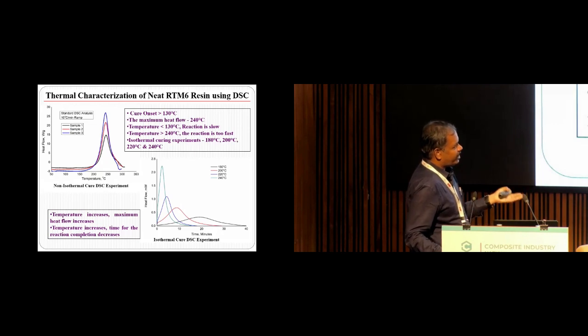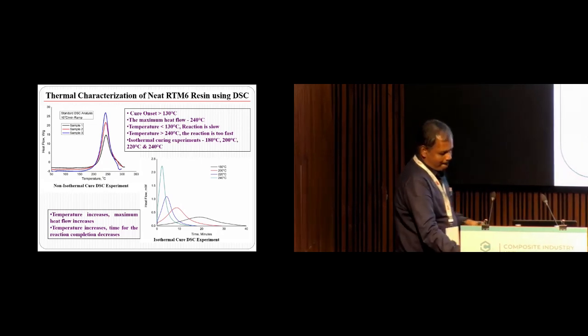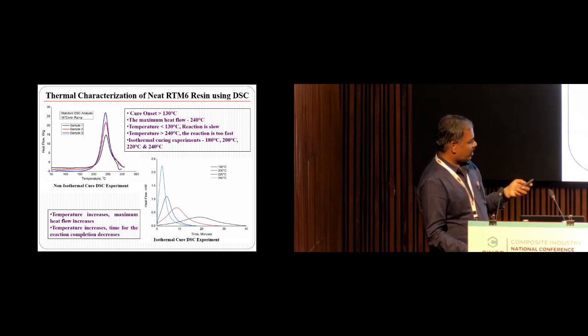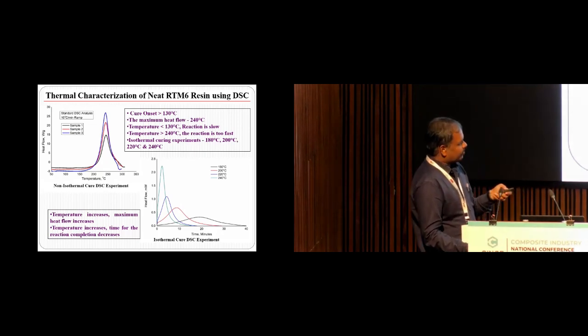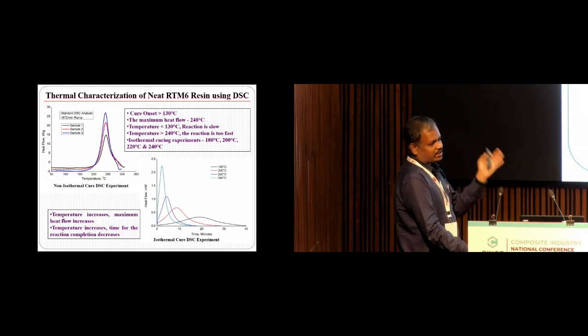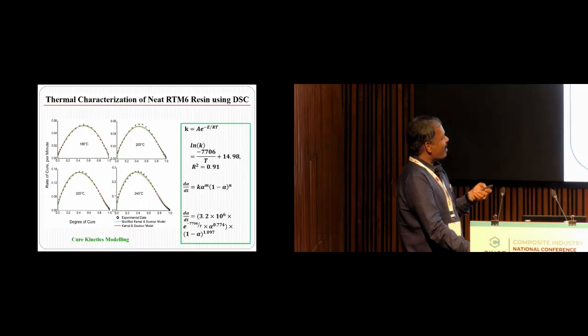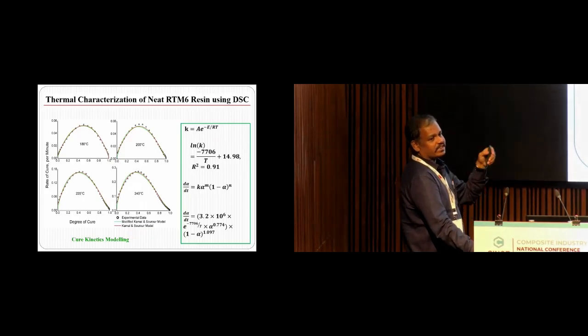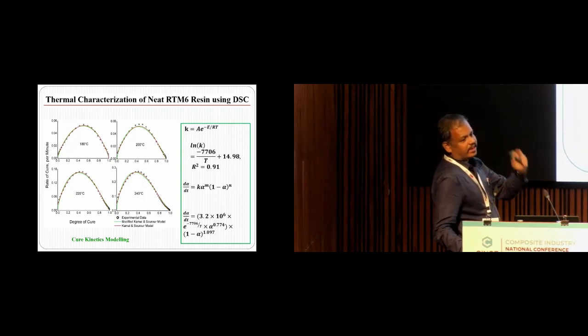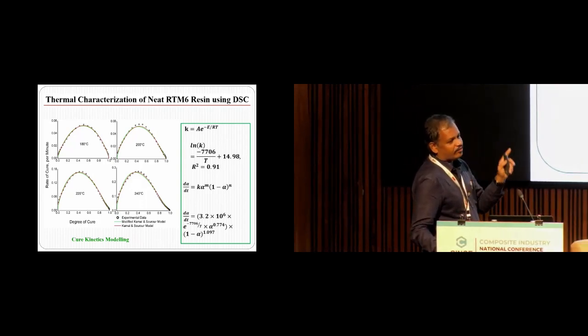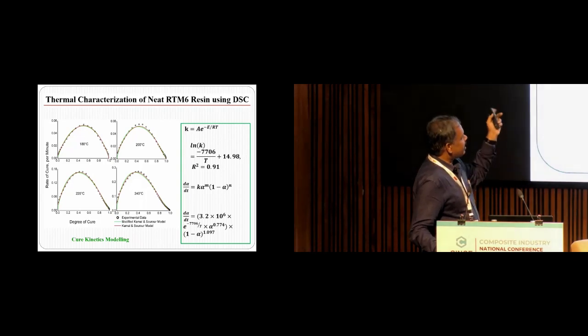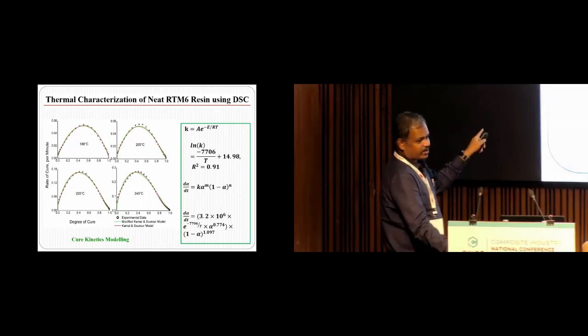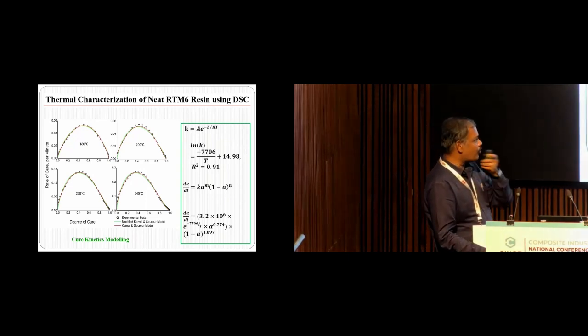You can see 180, 200, 220, and 240 degrees centigrade, and I got the heat evolution behavior. Once I get the isothermal heat flow curve, I discretize the partial area by the total area, and I can plot the degree of cure. After getting the degree of cure versus time for different isothermal temperatures, I can differentiate again and get dα/dt, which is the rate of cure.